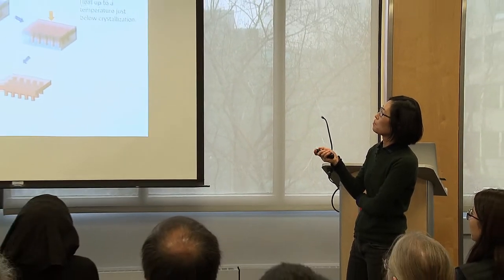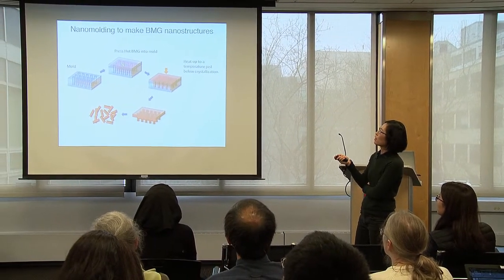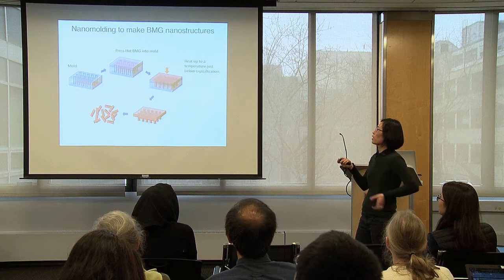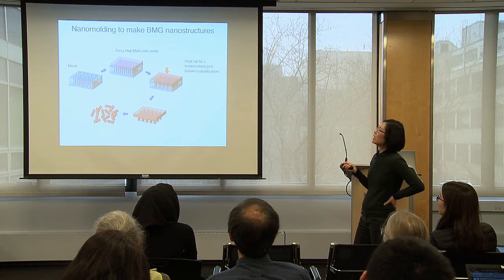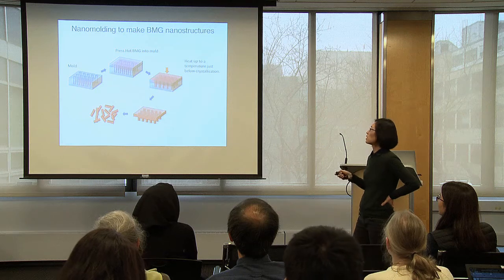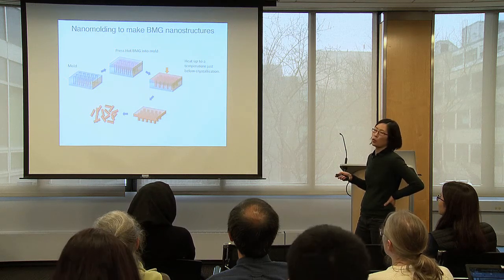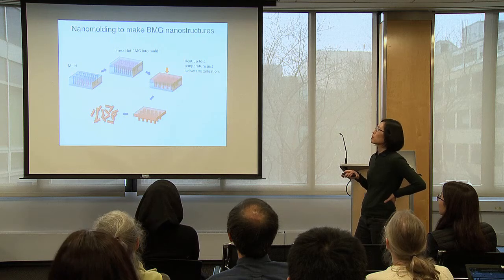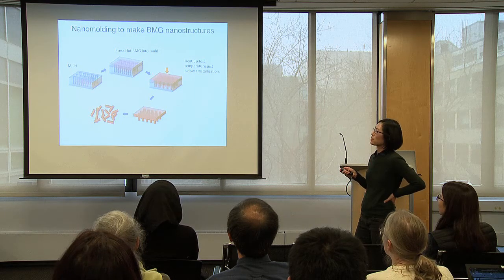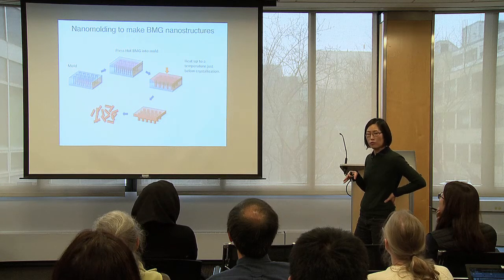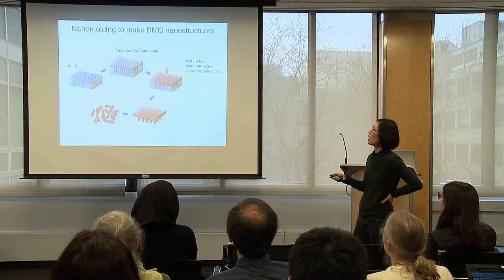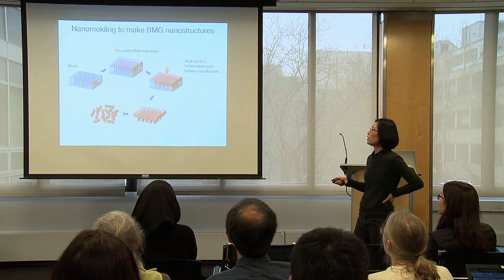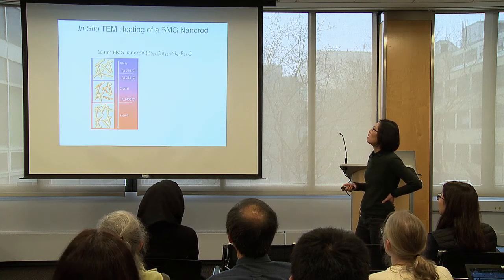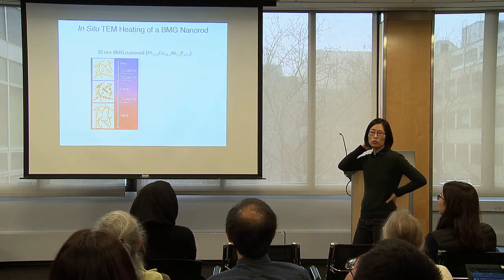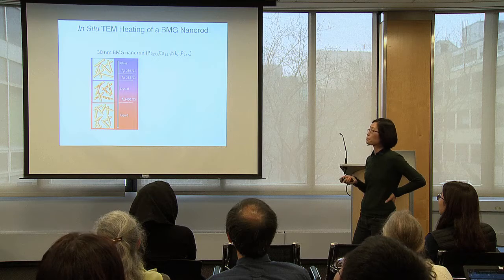The way we make this is you first have a bulk metallic glass film, a micrometer-thick plate. Then you heat it a little bit, but still below the glass transition temperature, and you push it through a mold, which is anodic aluminum oxide. Because it's at a somewhat high temperature, it's kind of viscous, so you can push it through. Then you etch away the mold, and sonicate to break off these rods. So you collect them, and you can imagine just drop casting these onto a heating holder chip.